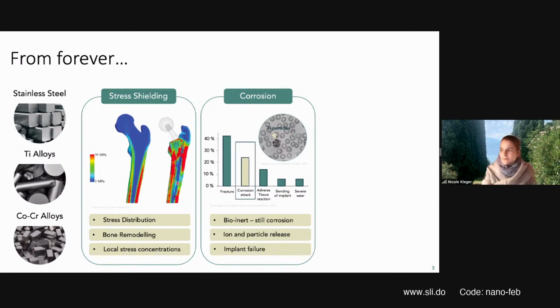And what you see on this chart is that corrosive attacks are actually one of the most often reasons for implant failure. So it's up to more than 20% of the implant failure is actually because of corrosion attacks. Now, this releases ions into our body, and sometimes in the case for chromium cobalt, for example, these are even toxic for our body. But it's not only the ions, also particles are released. So as you see on this picture, these are red cells, and these black dots here are titanium particles that accumulate in the blood.